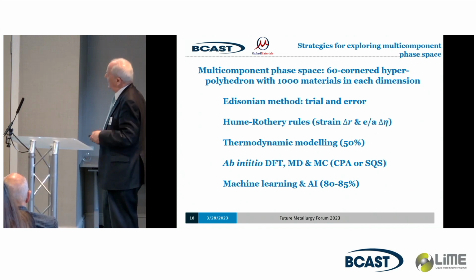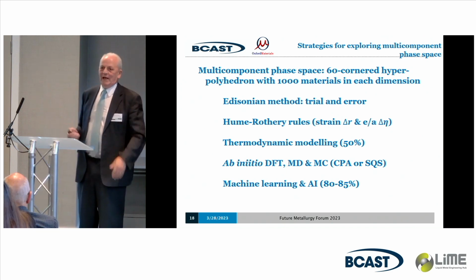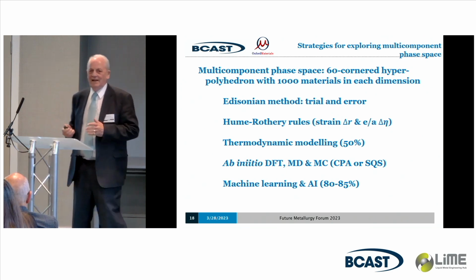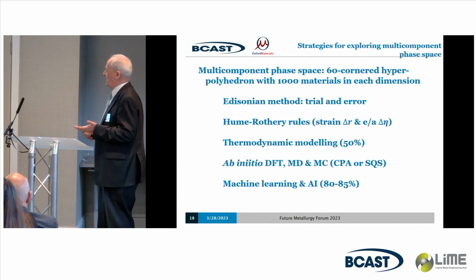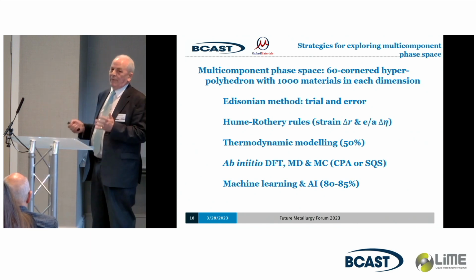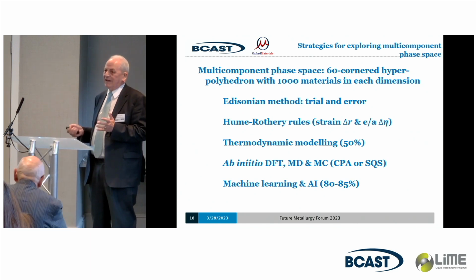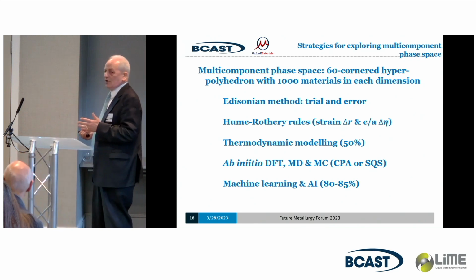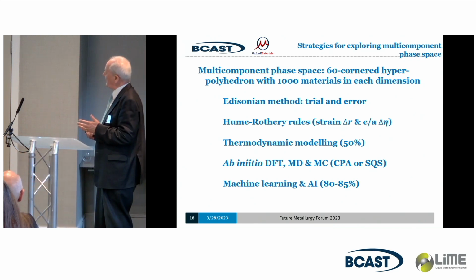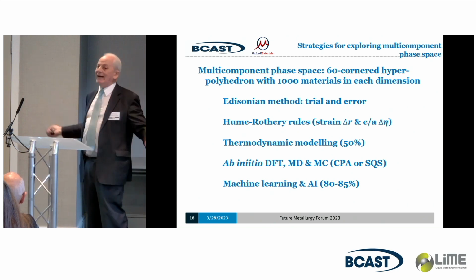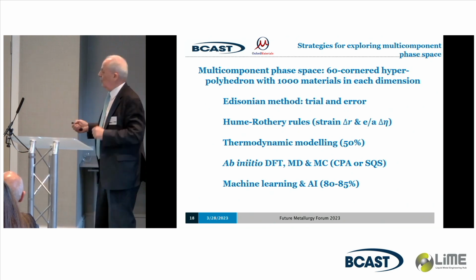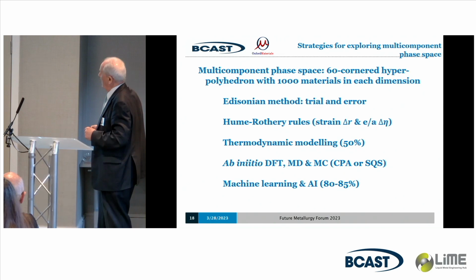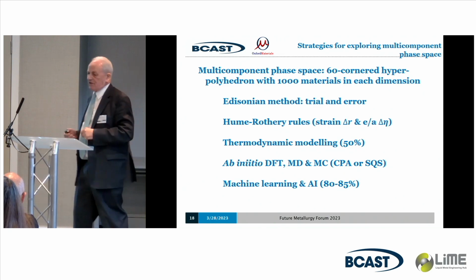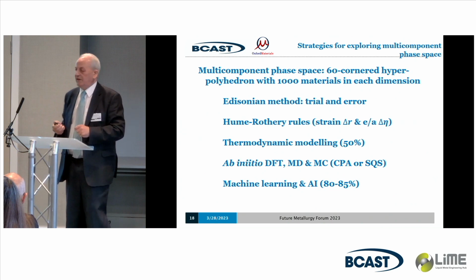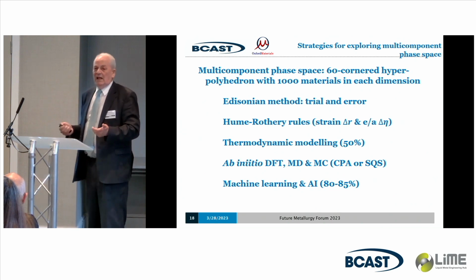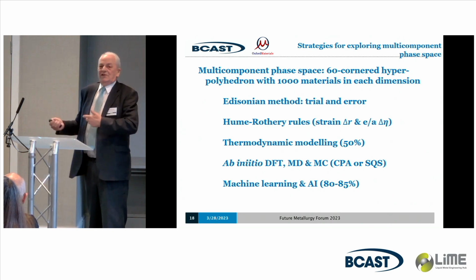And then the atomistic modelers said, we can do it all with ab initio modeling. No, you can't. You can't do it. Ab initio modeling is wonderful, but you can't do proper ab initio modeling with more than about 20 or 30 atoms. And if you want to look at a random structure, there are two ways of doing it. You either have to have a mean field assumption, and that washes out all the difference of the different components, which I will show you is important in a minute. Or you have what's called a supercell, where you randomize it, and you again wash out all the differences.